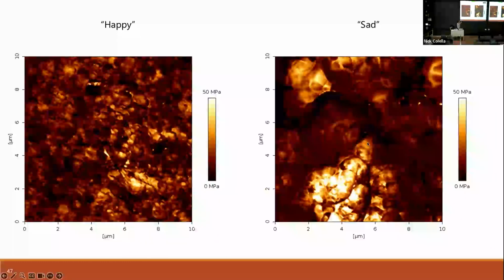Interestingly, for the sad ball, and this is where we really can start to learn about both the chemical and physical properties of it, we see some stiff regions and also some soft regions. So for me, this tells us that we have kind of maybe two different materials present, one soft material and one stiff material. So the happy ball is a cross-linked polybutadiene. So all polybutadiene cross-linked with sulfur vulcanization, and that just makes a standard rubber bouncy ball.